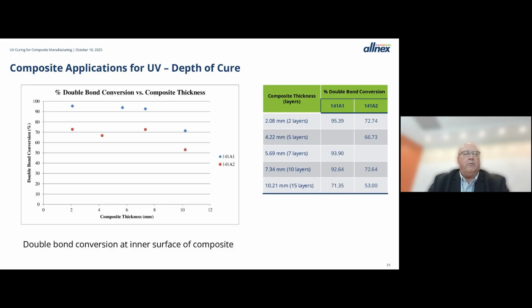And if we look at that, we did some experiments where we varied composite thickness and tried to cure it, and then looked at the double bond conversion on the bottom of the composite, or the side opposite the lamp. And as you can see here, we had two different formulations, but they both behave the same. Up to about 8-9 millimeter thickness, you get very good cure. Once you get beyond that, you still get a cured material. It's a solid material, but if you measured either conversion or Tg or some physical property, you're going to see that property start to decrease when you get up around 9-10 millimeter thickness.